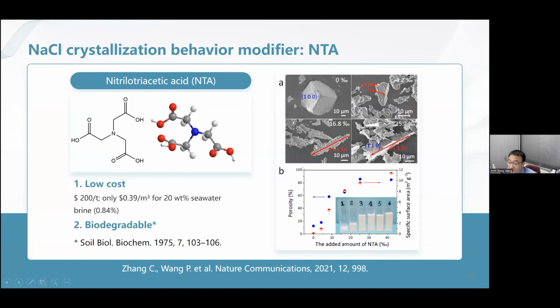Now, pay attention to figure B at the bottom right. See, the same amount of the sodium chloride solution with the same concentration, with different amounts of NTA being added. You see, without any NTA, this solution produces this amount of the salts. The bulk volume is this much. With a little bit of the NTA being added, you see at a certain point, you enhance the bulk volume from this little to this much. So this chemical can really, selectively, enhance the porosity of the sodium chloride.